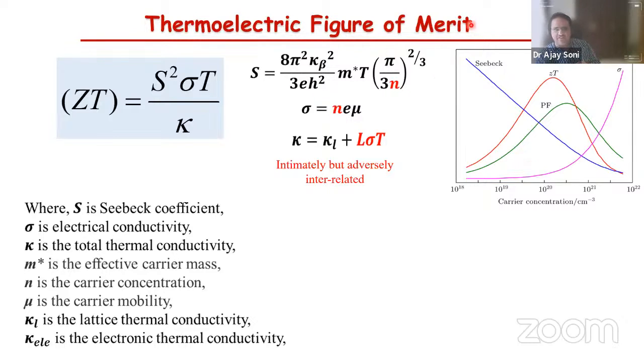It's called the thermoelectric figure of merit, and this is defined by the mathematical formulation ZT equals S squared sigma multiplied by T divided by K. So if you understand this equation, half of my job is done. S is the thermoelectric power of the material, which is the Seebeck coefficient. Sigma is the electrical conductivity of the material. K is the thermal conductivity of the material, and T is the temperature, the operating temperature where this material can be functional.